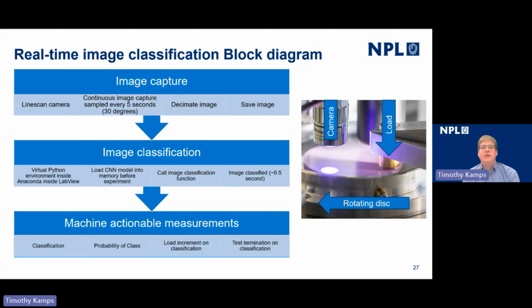So we can have a very small load increment with a time period. We can slide over a fixed distance, and we can keep asking the system to evaluate the wear mechanism. And every time that we've reached the end of our time increment and we haven't seen the transition that we're expecting from abrasion to adhesion, we can then increment the load, and that allows a fully automated experiment where we can move around until the failure is just about to occur. At this point, we can decide what we'd like to do, whether we want to fix the load and run the test just at the point of the wear mechanism transition, or whether in fact we actually want to stop the test and terminate it right as the transition's beginning to occur, and then evaluate the surface using ex situ analytical techniques.